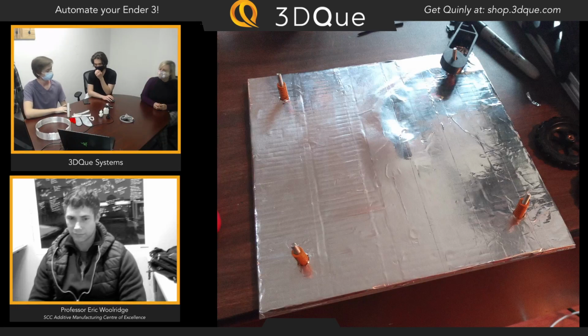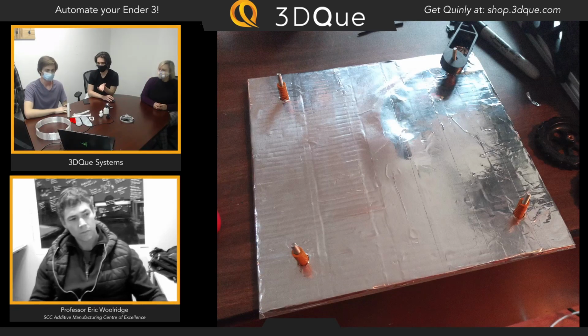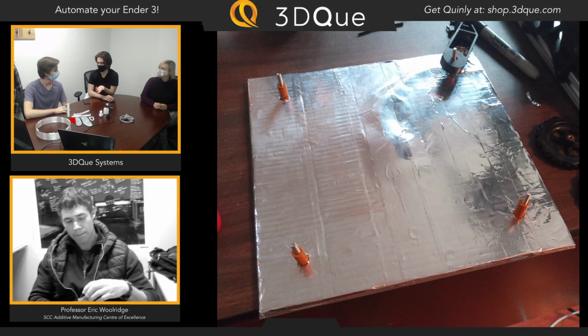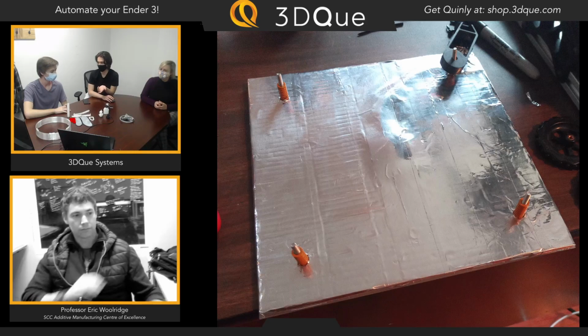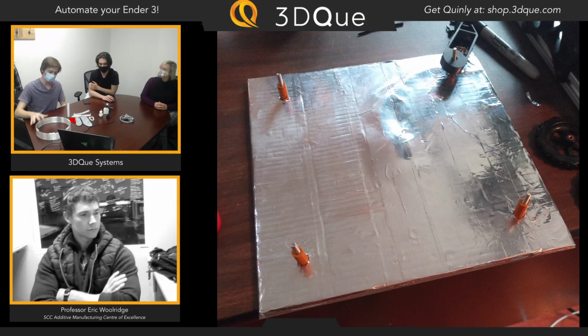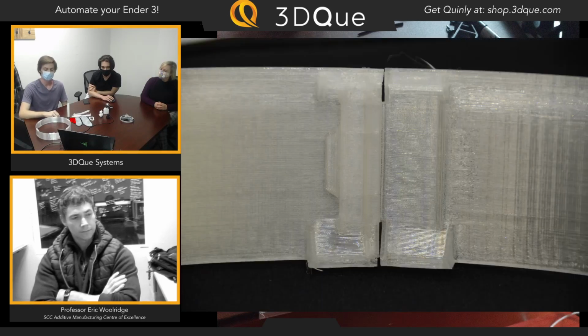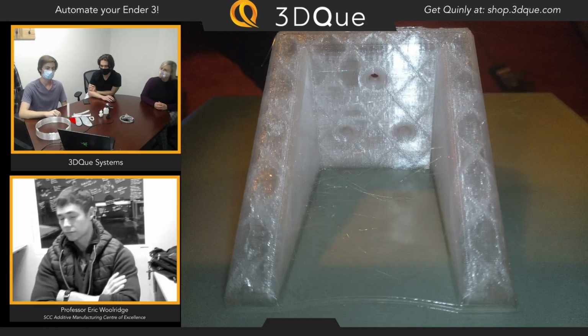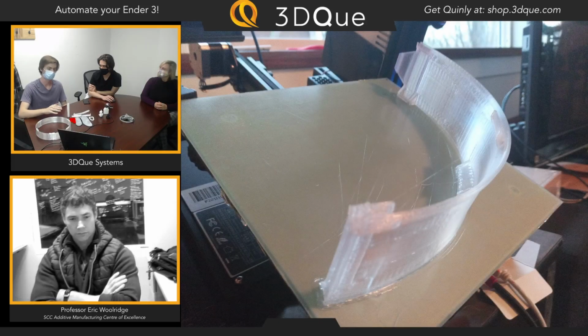And so what is really fascinating about getting polycarbonate to print on an Ender is that an Ender is a completely open printer, right? Heat loss and the heat gradient from a really hot bed to a really cold ambient temperature is a major driver of warping. So did you find that warping was an issue with these? With polycarbonate, warping is a little bit of an issue. I found a few things that you can do to improve warping is simply just crank the bed up, because I think it warms the air around the part a little bit, and that helps smooth the gradient out a little bit.